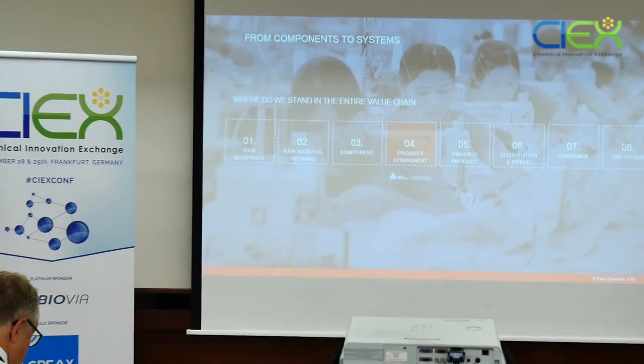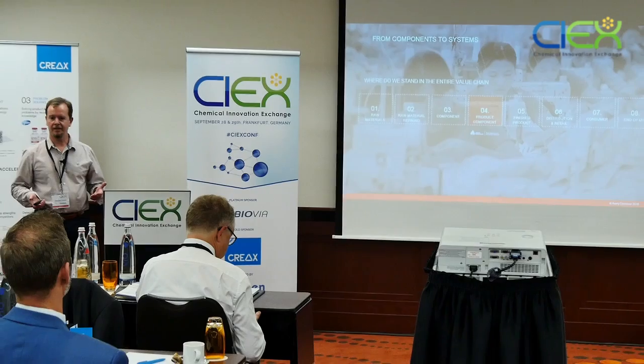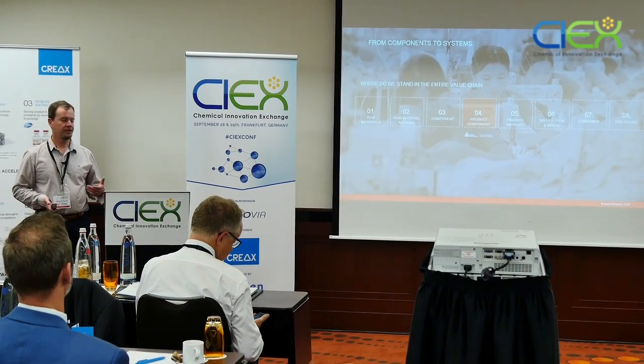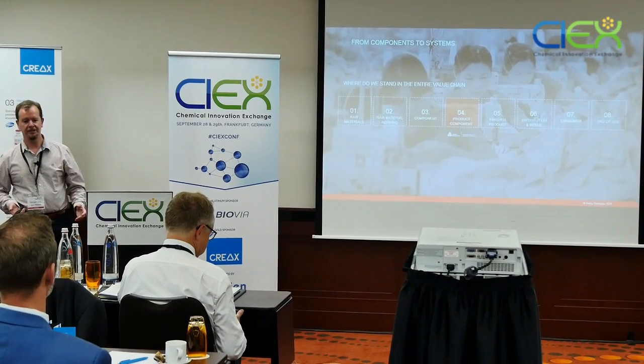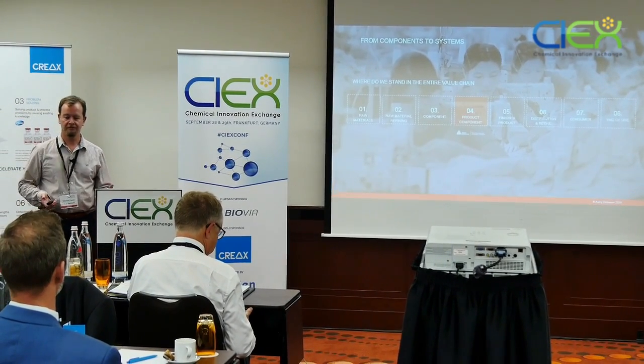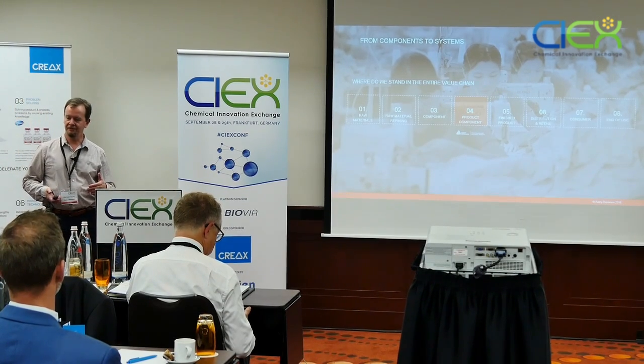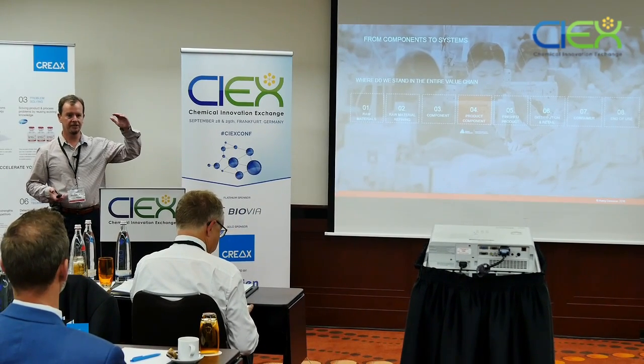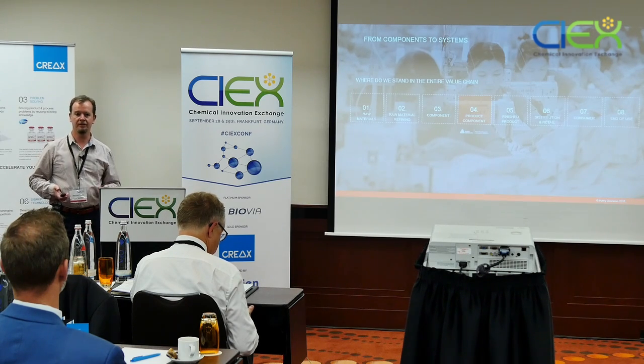Typically these things are made in factories in China or Vietnam or India, but then they're shipped for sometimes 8, 10, 12 weeks on the water. So when you design a new material, you have to consider that you want to change your adhesive, for example. Someone says, I want an APEO-free adhesive. REACH is telling me I can't have APEO surfactants in my products. You've got to get them out. So we redesign it, but then you have to test it. Because if that adhesive goes on a garment and then sits in a container at God knows what conditions for 12 weeks, it could be 50, 60 degrees in a container, with humidity variation across the globe. When it gets to the other end and you remove that label, you don't want any residue left behind. You've ruined the garment with one tiny strip of self-adhesive material if you do that.